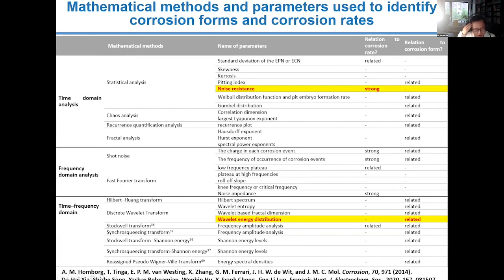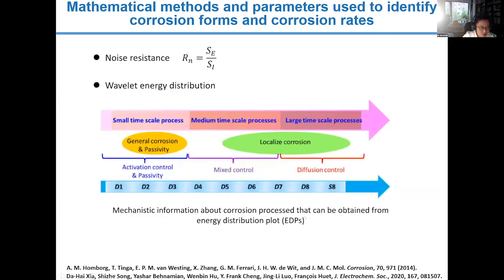This table lists most of the mathematical method and parameters used to analyze EN data. I'm not going to introduce each of them in details, but only mention 2 of them. One is noise resistance, and the other is wavelet energy distribution. Noise resistance is defined as the ratio of standard deviation of the simultaneously measured potential noise and current noise signals. So it is inversely proportional to corrosion rate. And for wavelet energy distribution, noise signal can be decomposed into several signals named as D1, D2, D3 to S8. D1 is a high frequency signal and S8 is a low frequency signal. For localized corrosion, the wavelet energy at low frequency is higher than that at a high frequency.